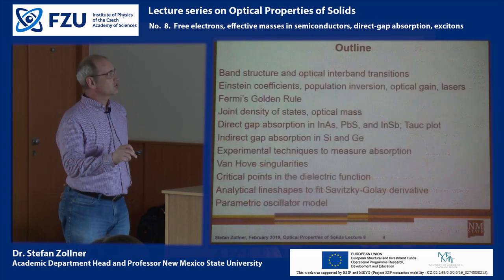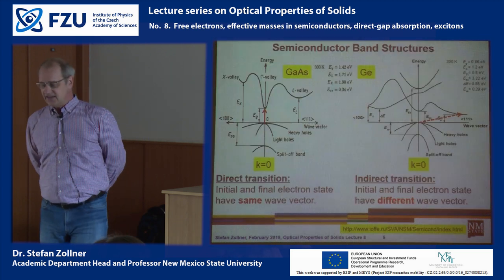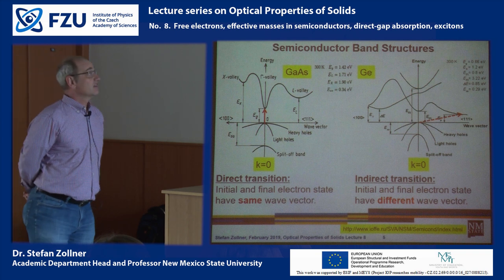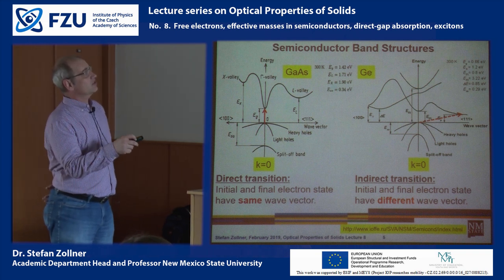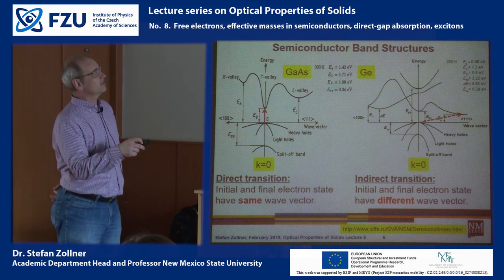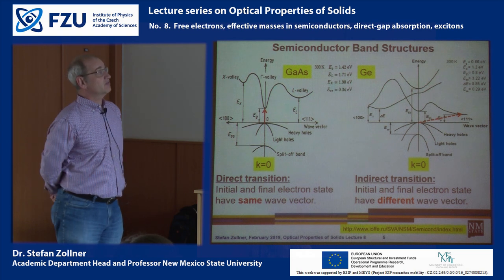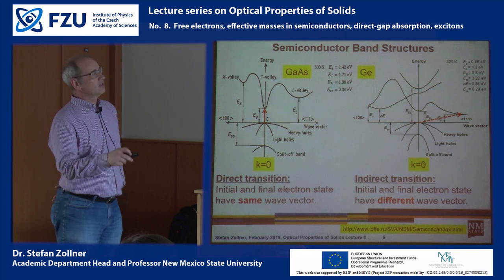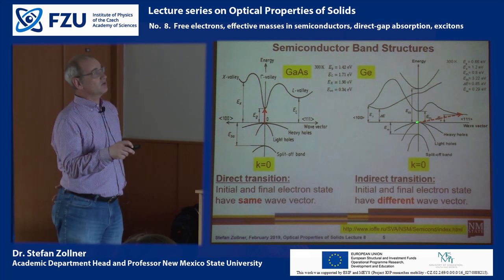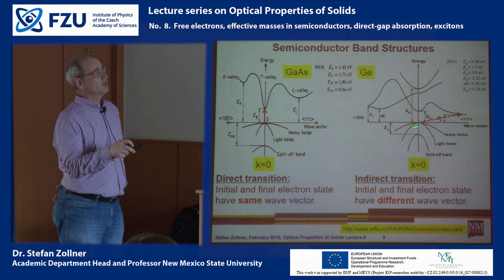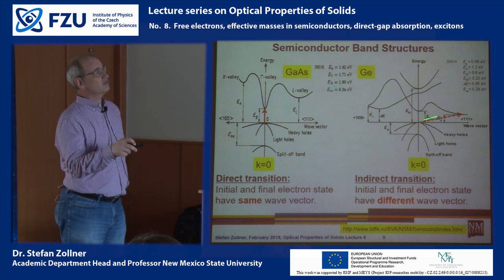At the end of the last lecture we looked at band structures of different materials. On the left we have gallium arsenide, which is a direct material where the initial and final states have the same wave vector — therefore the momentum change is zero. On the right we have germanium as an example of an indirect material, where the lowest transition occurs from the gamma maximum of the valence band to the minimum of the conduction band at the L point. If an electron-hole pair is excited across this indirect gap, then delta K is not equal to zero.